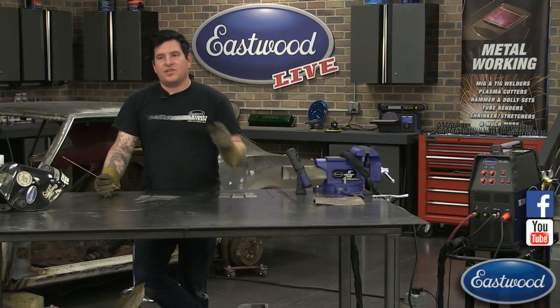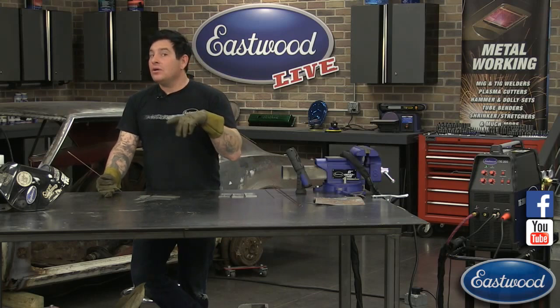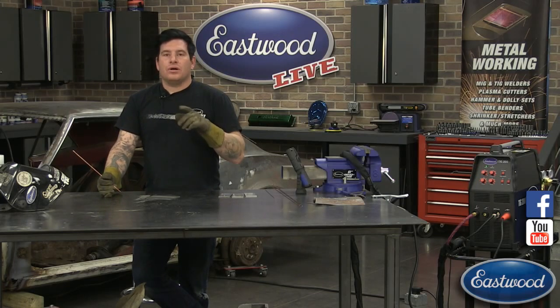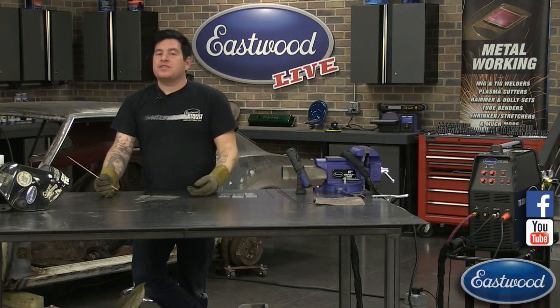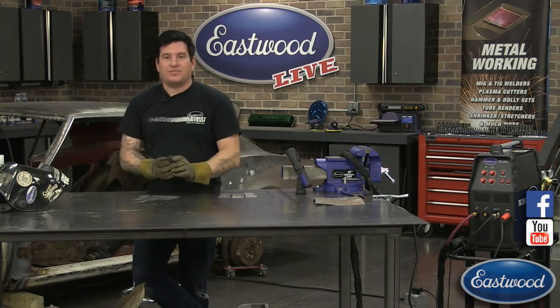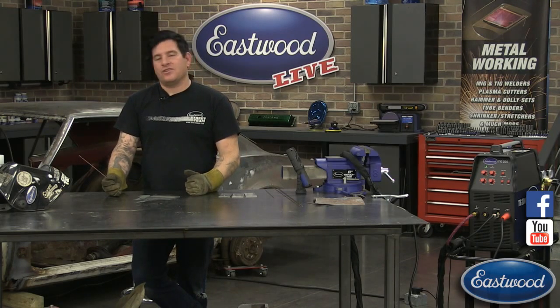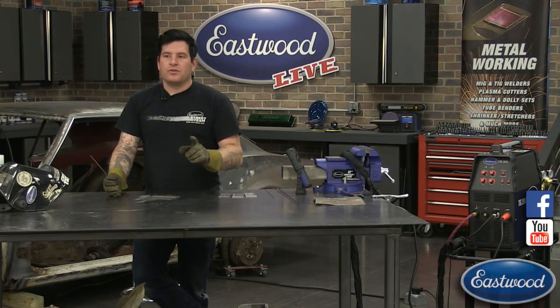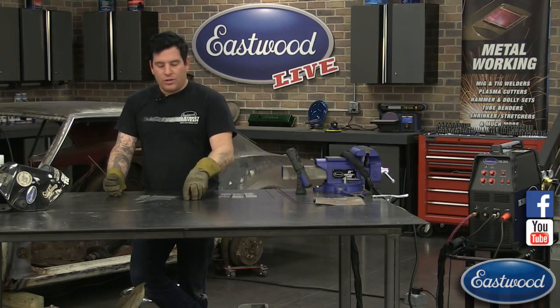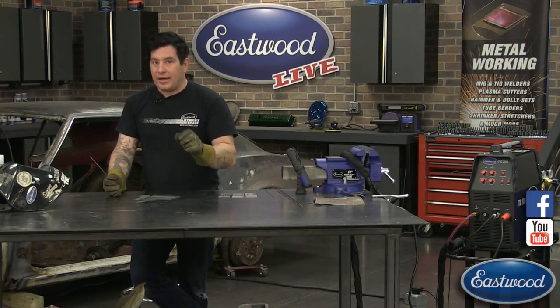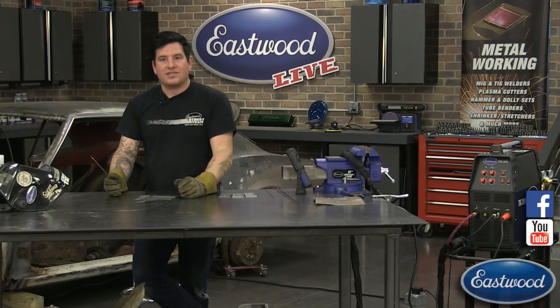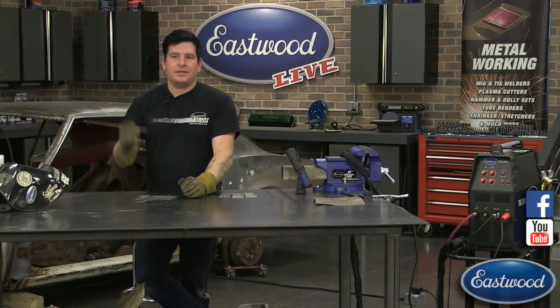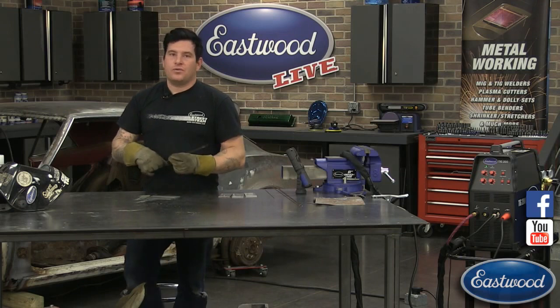So you'll see pits. If you see a black halo around your metal, like heavy black, that's probably an issue too, that's burning off whatever the dirt is. It's probably going to be a dirty weld. On aluminum, it's really easy to tell as well. You'll see little pieces of dirt actually in the weld. You'll see little black spots in it. But the biggest thing is if you see pitting in the weld, that's a quick way to tell.